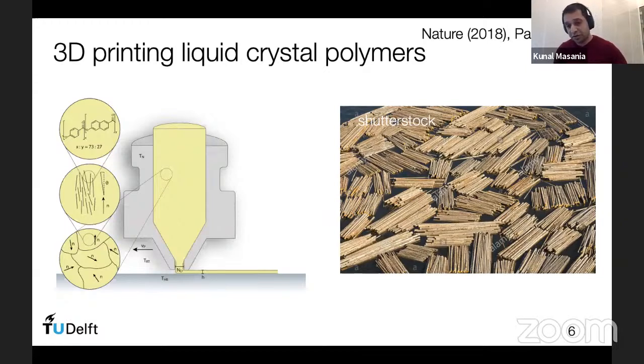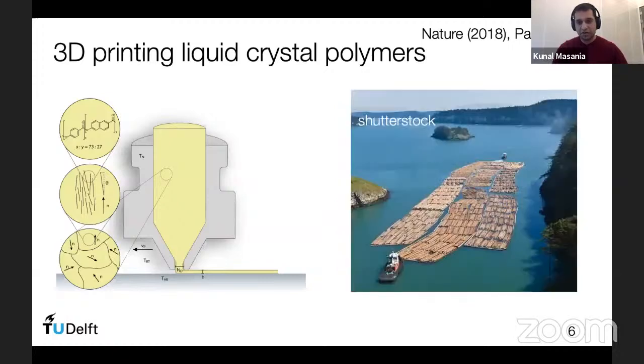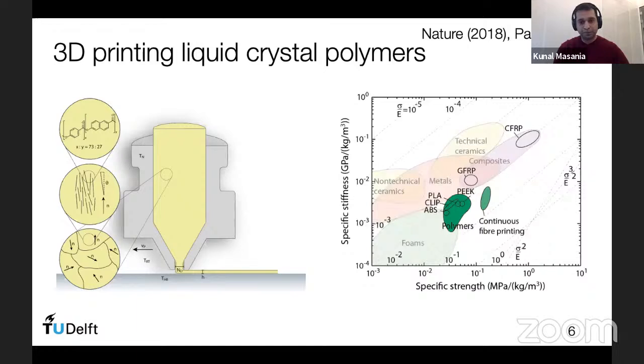And they have a very special trick to them, which was established and well known from the 80s. And that is that when you apply heat to thermotropic LCPs and you apply shear, you can create orientation in the materials. So here I'm just showing some logs in a sea, and you can see through the constriction they orient. And for us, we hope that with the printing, similar approaches can happen.